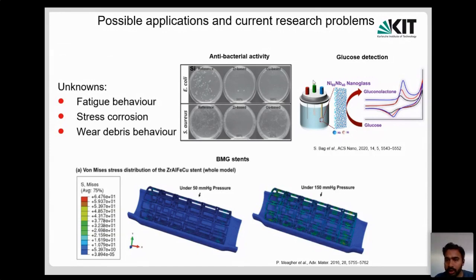And recently our group has shown that nickel niobium nanoglass can be used as some kind of glucose detector. So you can use them as glucose sensors. They show enhanced glucose activity because of the increased surface area and roughness. And recently there are applications to use them as stents in the heart, where when the heart valve gets clogged or something, people put in stents so that the blood can flow through. For that stent, you need some kind of solid structure which is very strong, which does not corrode, and which can stay long. For that, they have tried to use bulk metallic glass, and this is a model where they try to calculate the von Mises stress distribution to see how strong it will be. And this is an interesting approach to go to biomedical applications.